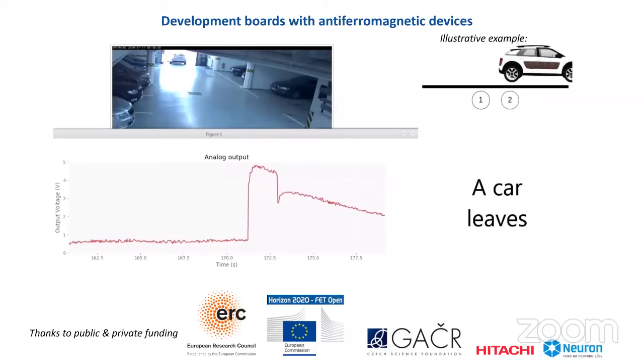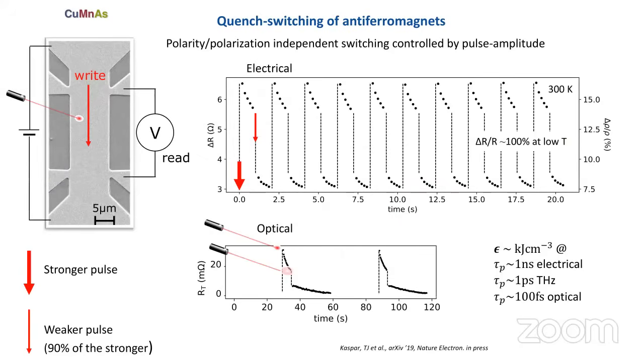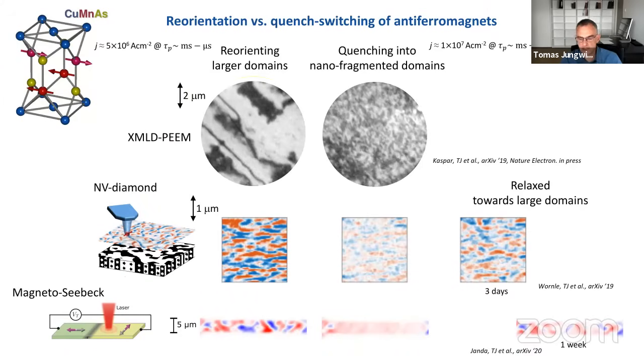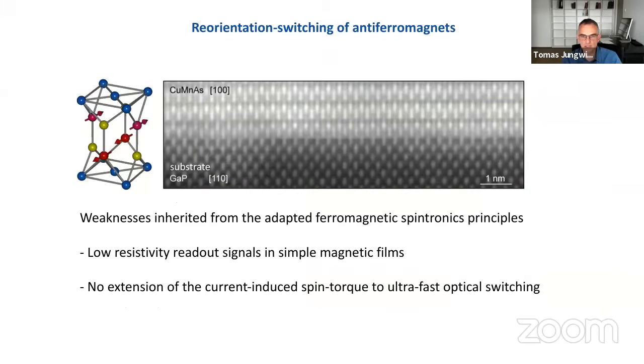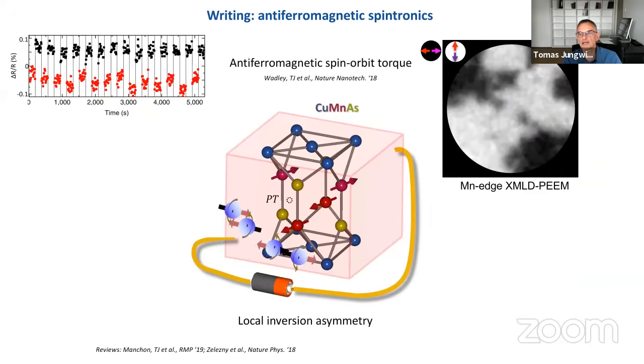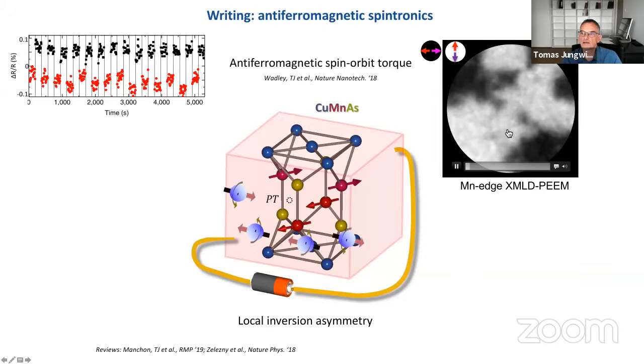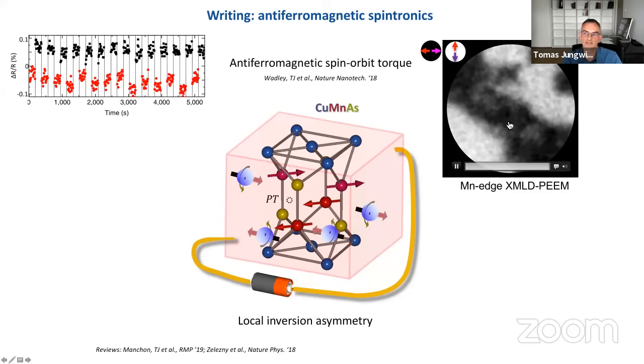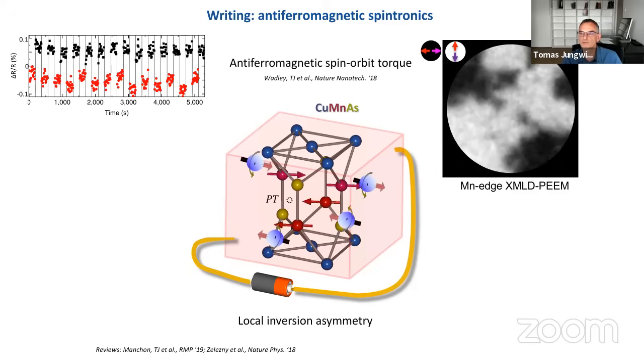My question relates to your last topic, this intriguing quench switching, and whether you have an idea of the mechanism there. You said it's a different mechanism from the spin orbit related effects, but I don't think you discussed what it was. Well, we have images of what's happening. In our reorientation switching, what we see in X-ray magnetic linear dichroism is switching of large domains. It's the same material: you start with a pristine material and pulse it gently with weaker pulses, and then you see switching by 90 degrees of these several micron size domains. You can control the switching, for example, by the polarity of the pulse, so it has all the features that you expect from the spin orbit torque.